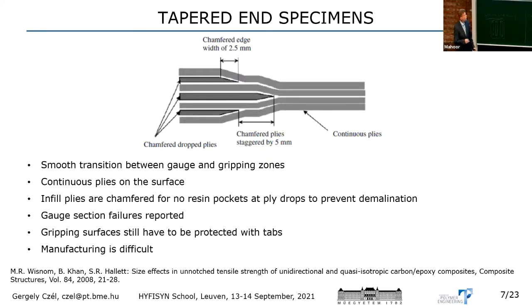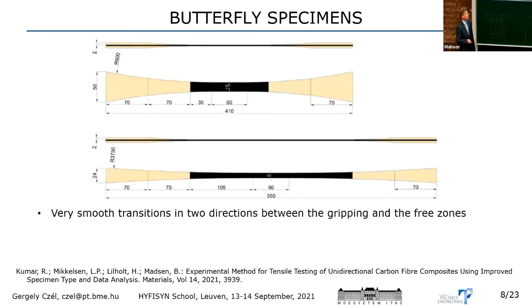So to do this, we actually need to put the same thickness plies to the continuous section, the gauge section, like space holders, and then we scrap that one. We cure the whole thing, but we only use part of it, and so it's really an advanced technique, and it's complicated, but might not be feasible at an industrial scale, let's say. But nevertheless, gauge section failures were reported with this approach, which was really promising.